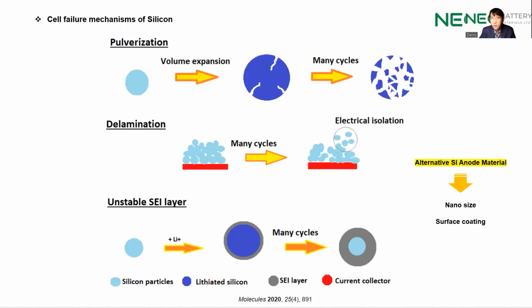However, successful implementation of silicon as an anode material has been restricted by the following drawbacks. If you see here on the chart, first, the large volume expansion induced by the charge and discharge process causes electrical contact loss or delamination. In the second part, there is continuous formation and growth of the solid electrolyte interface.